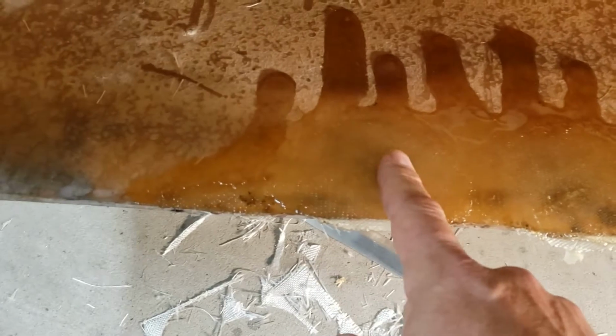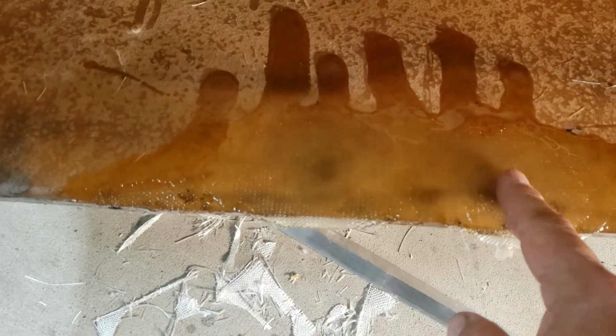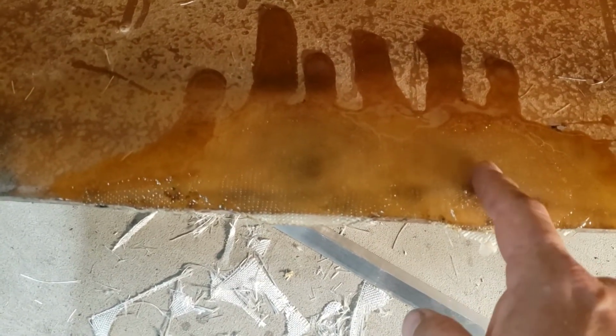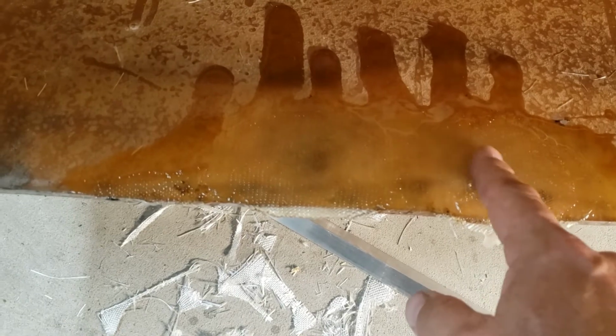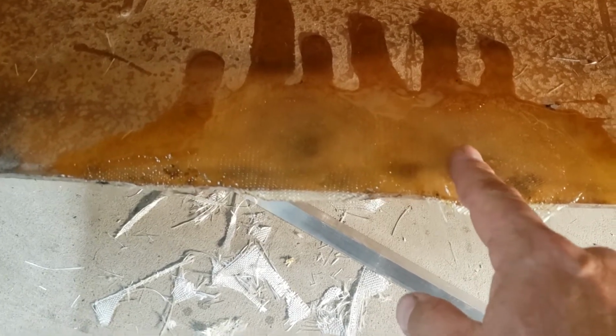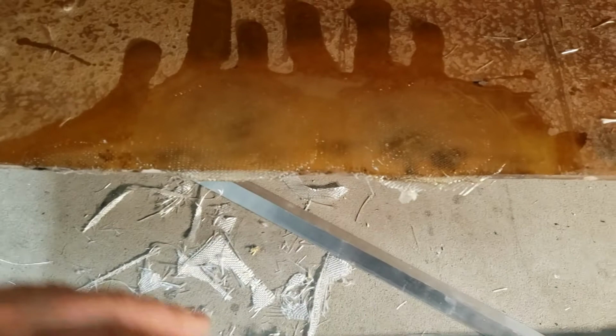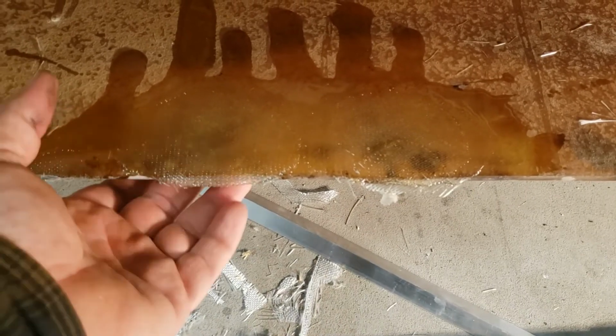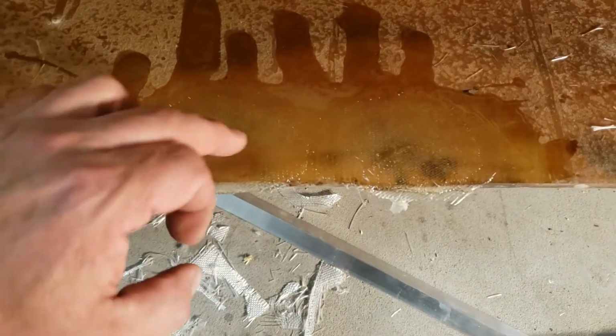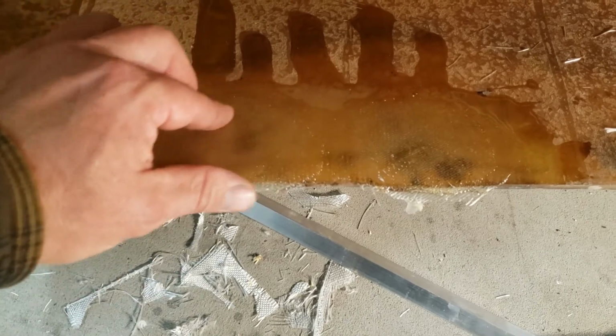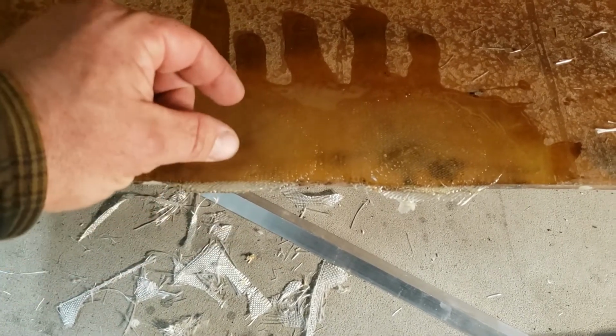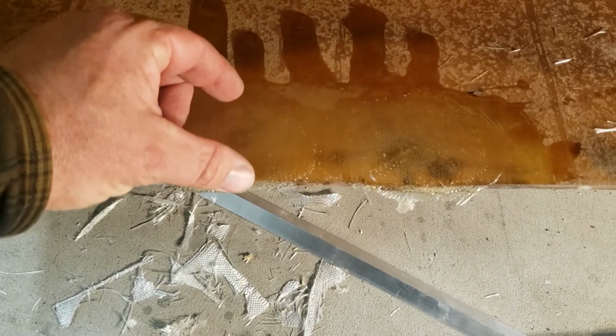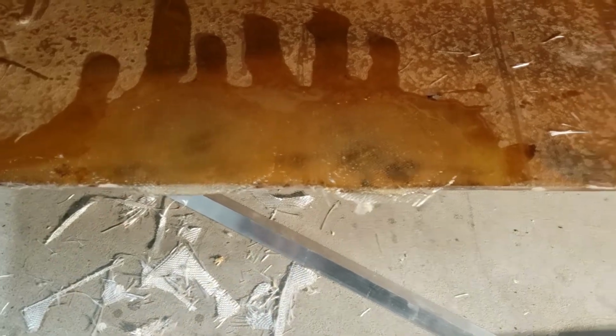But where these holes were, I used a microfiber slurry, if you will, epoxy with milled fibers blended into it to fill the hole initially, and then I did about 10 layups of coarse bid on top of it, small, you know, sequentially getting bigger layers. And now I'll trim all this up this morning.